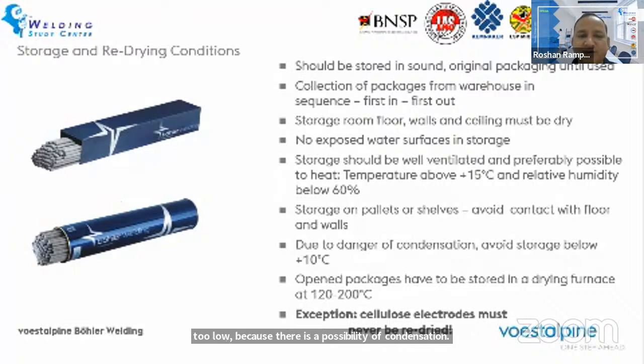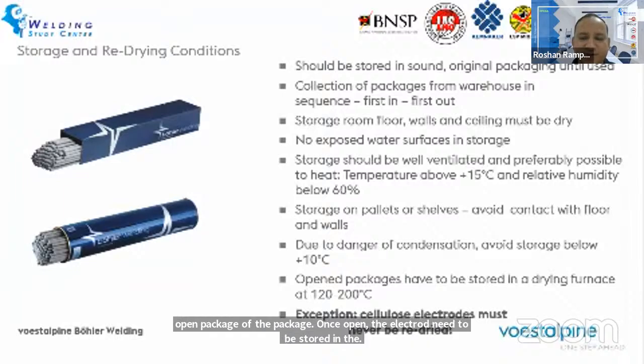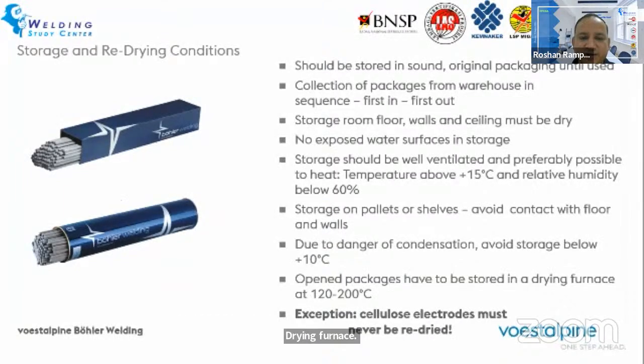Once a package is open, the electrodes need to be stored in a drying furnace, at a temperature recommended by the manufacturer of the products. One thing to highlight here is that cellulose electrodes must not be re-dried. They should be used in as-is condition because the cellulose has some hydrogen or moisture content which is necessary to get the desired arc intensity.